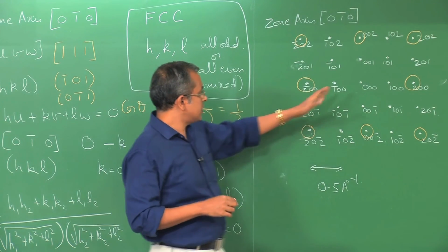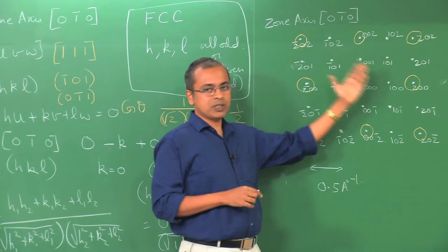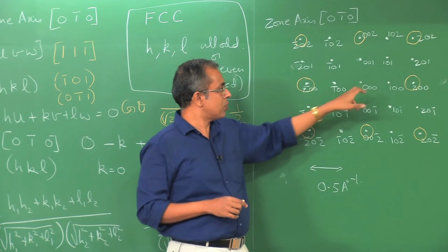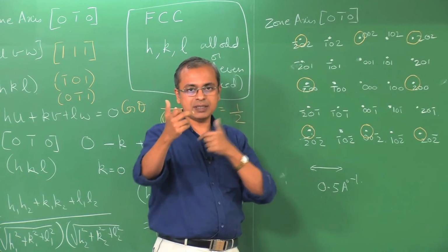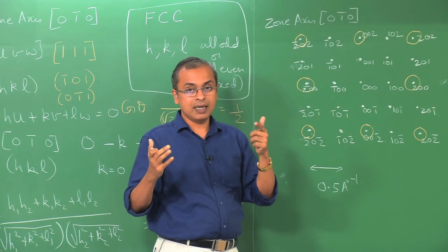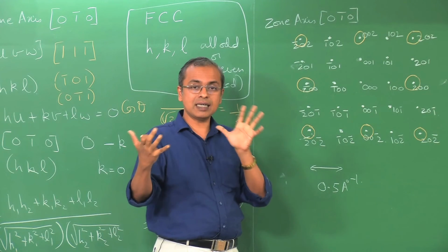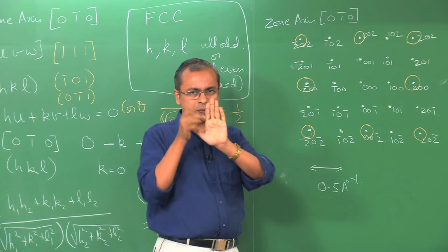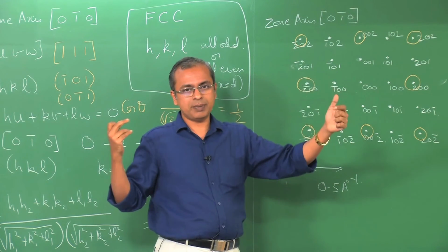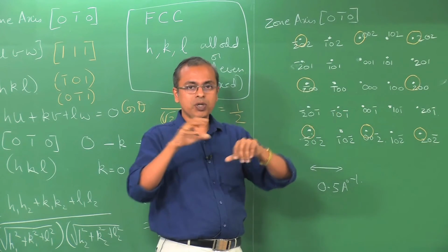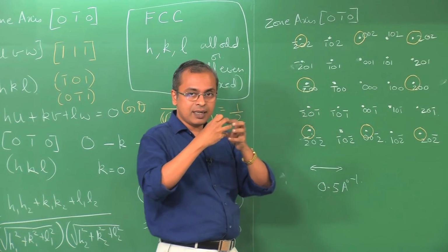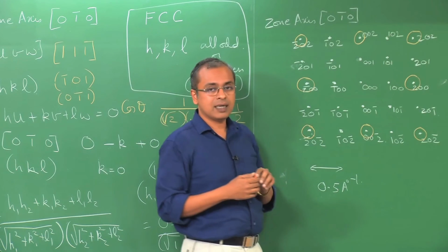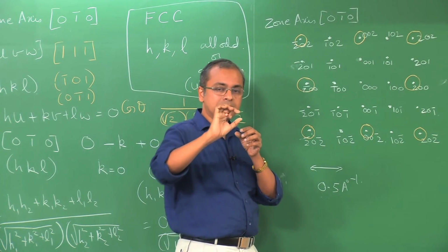So, what you see here is actually a slice in reciprocal space of points, and these are points now because we are talking of a large single crystal where the dimensions are all large in all dimensions. Supposing instead of a large single crystal, you had a thin film. So, by definition a thin film is very small in one dimension, and very large in two dimensions, right. So, corresponding to it, the intensity of a spot in the reciprocal space actually becomes a rod.